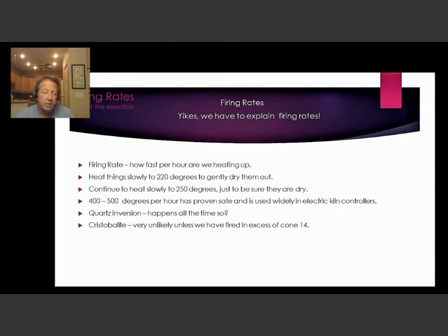And then the best cautionary note ever is heat everything up slowly from room temperature to, and I'm just going to say 250 degrees. And why is that? Because water boils at 212 degrees. So we want to be sure to remove all the moisture from all your pots, and that'll go a long way to helping them not crack due to steam generation.